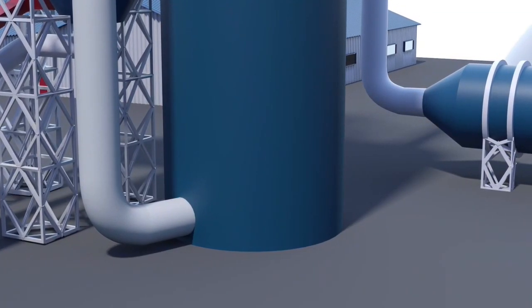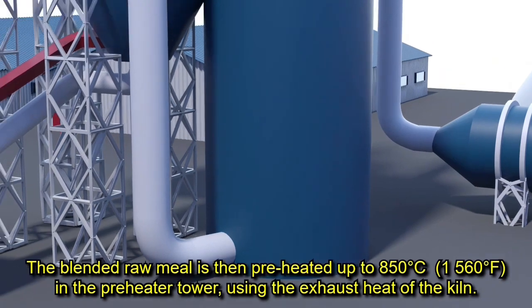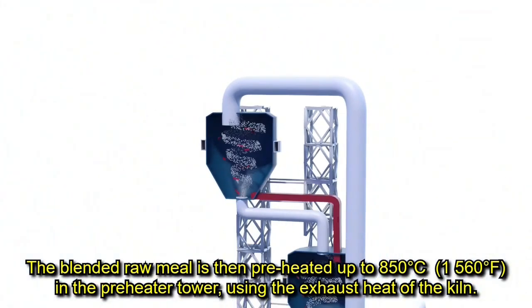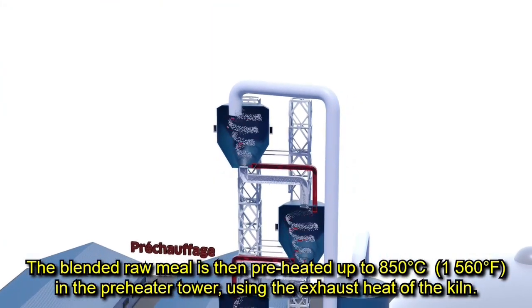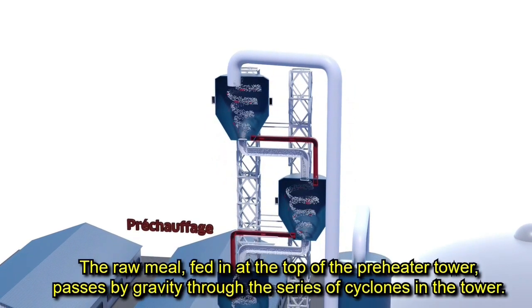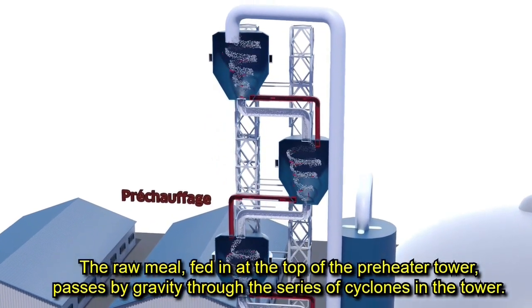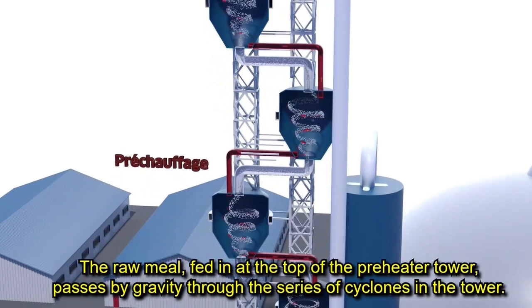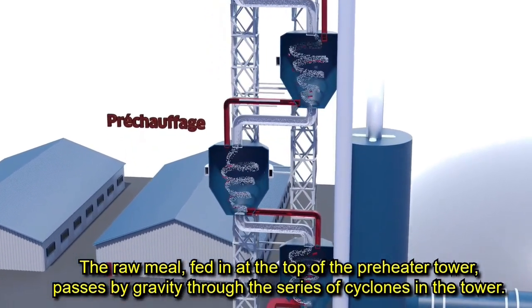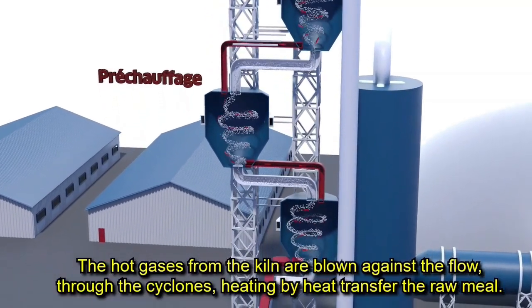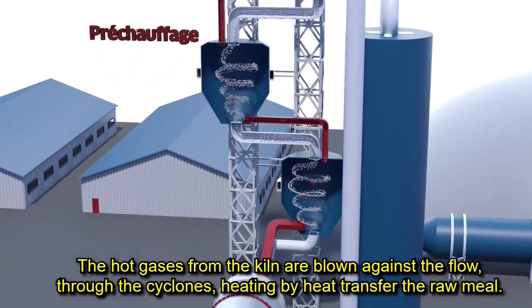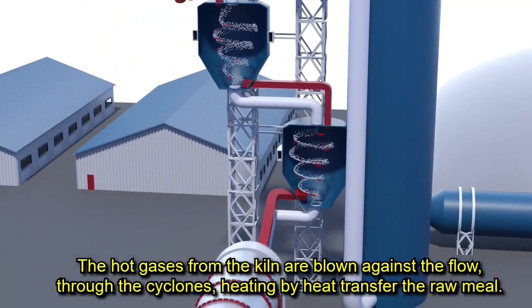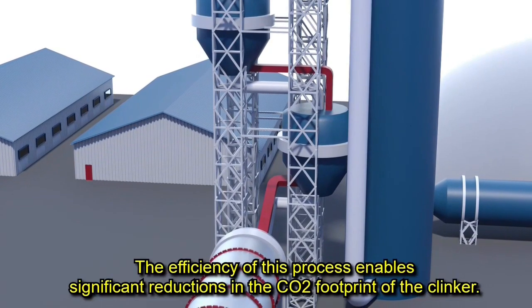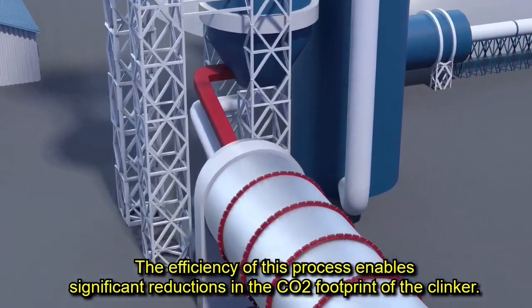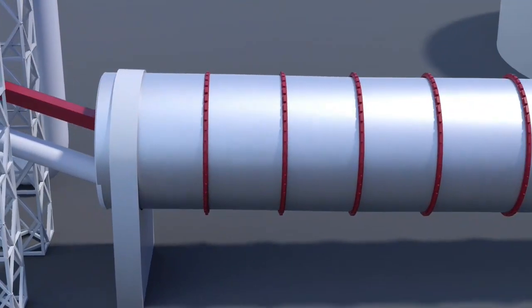Preheater. The blended raw meal is then preheated up to 850 centigrade in the preheater tower using the exhaust heat of the kiln. The raw meal fed in at the top of the preheater tower passes by gravity through the series of cyclones in the tower. The hot gases from the kiln are blown against the flow through the cyclones, heating by heat transfer the raw meal. The efficiency of this process enables significant reduction of the CO2 footprint of the clinker.